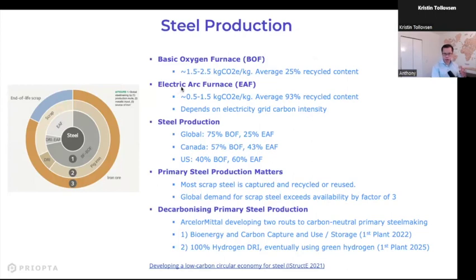Now, the electric arc furnace approach, as the name implies, uses electricity. So the carbon intensity of your provincial electricity grid mix will impact the carbon intensity of your steel, and that's something to keep in mind. In Canada, I think we're about 57% basic oxygen furnace and 43% electric arc furnace. Some of these numbers may have changed a little bit, but we're roughly in that range. And as I mentioned earlier, we still need to think about how to decarbonize primary steel production, because global demand for scrap steel exceeds the availability by a factor of 3. So there's 3 times the demand compared to the amount of recycled steel that's available.